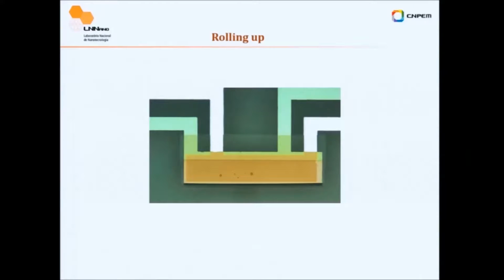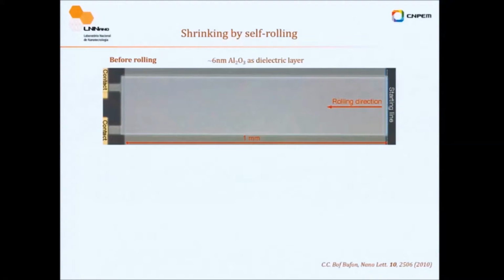So this is an old example of how the system rolls. This case is not germanium, it's photoresist. And here's a typical case of a lithographic process done on a planar device. You can see 1 millimeter long, about 200 microns wide. This is before rolling. The dielectric here is aluminum oxide, 6 nanometers of aluminum oxide.